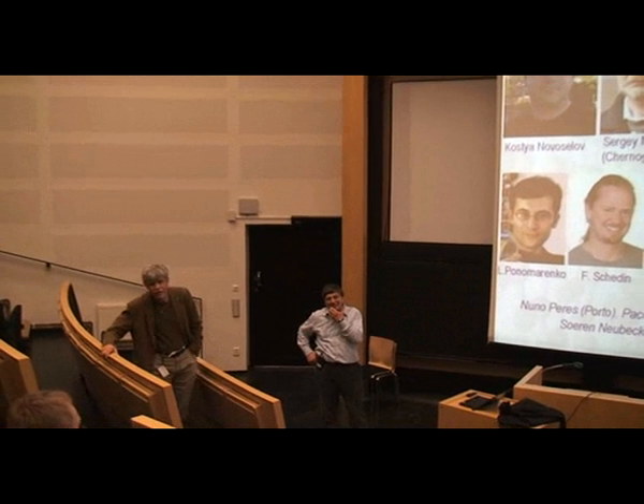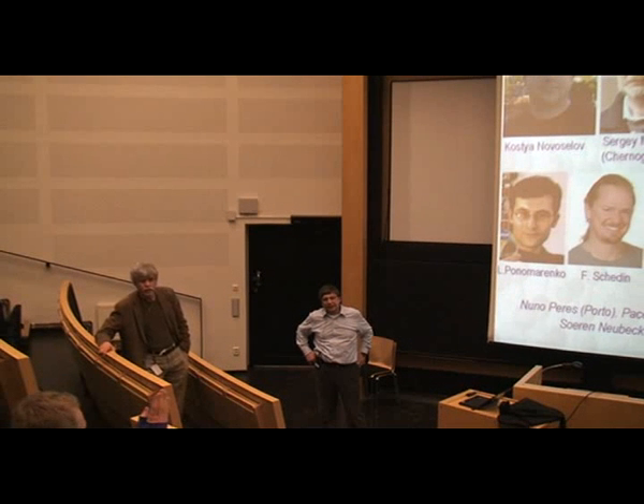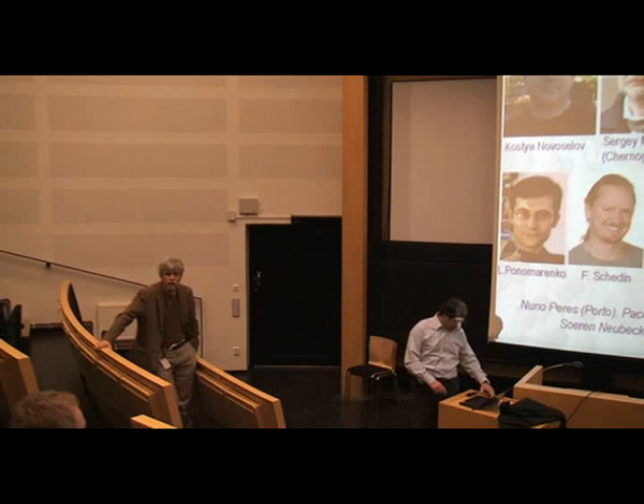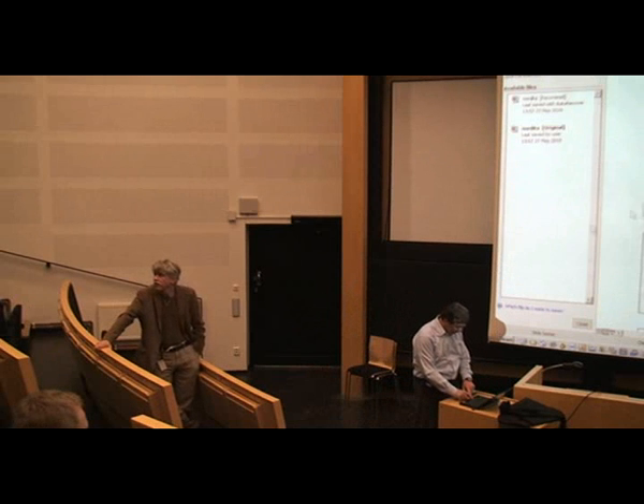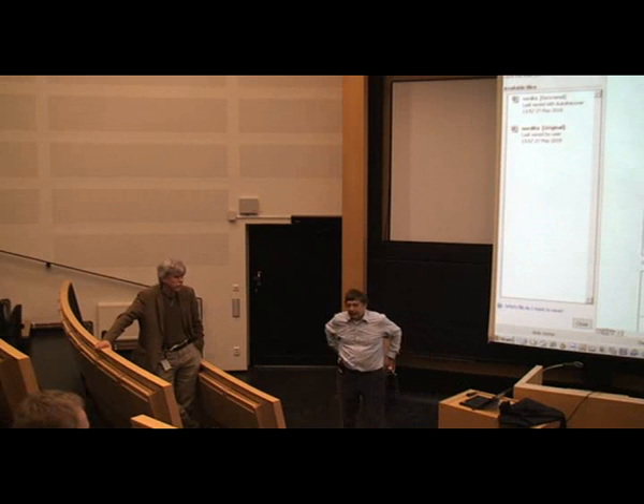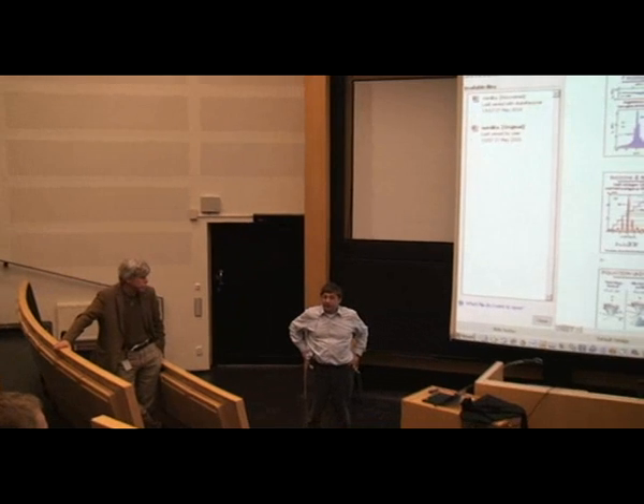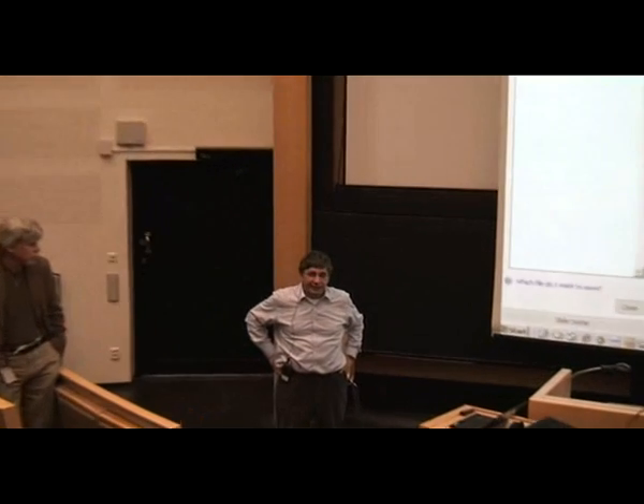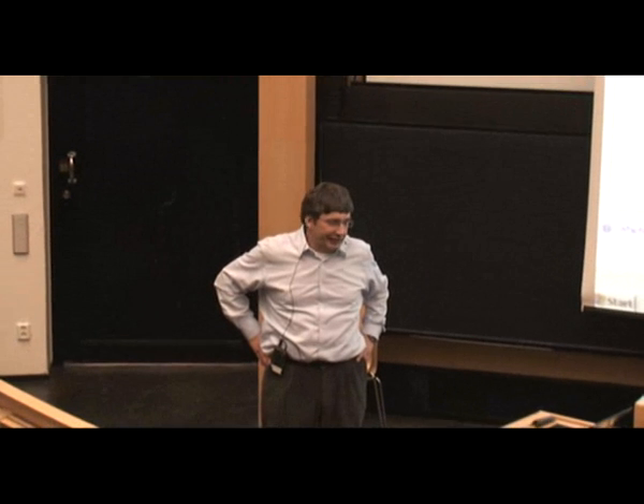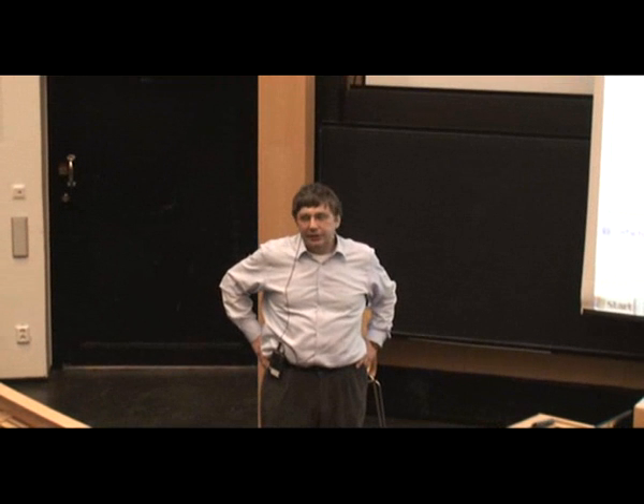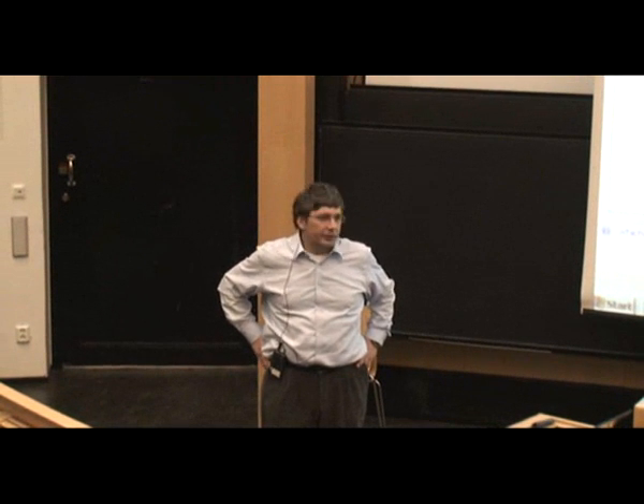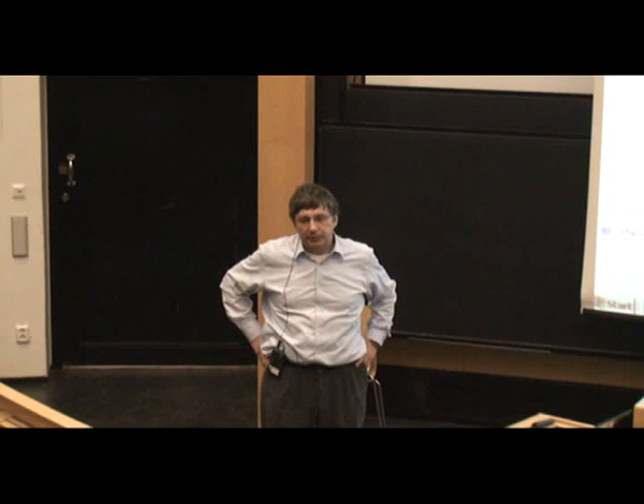Well, on the mechanical properties, you showed that single flake standing up. How sure are you that there is no electrostatic charge in that? The flake is conductive and it's on a conductive electrode. I'm not sure about electrostatic charge, but it stays. If there were electrostatic charge, it would be varying with time. Not only ourselves, but many people observe that. But there is no charge in effect. It's a conductive material, essentially a very highly conductive material.